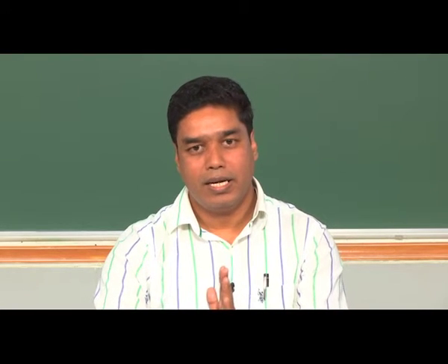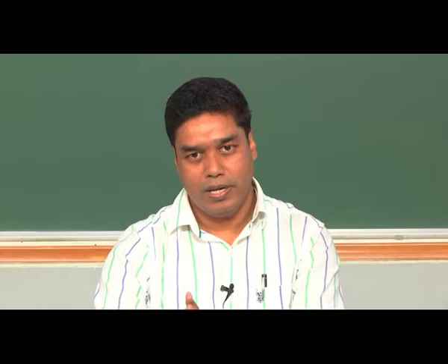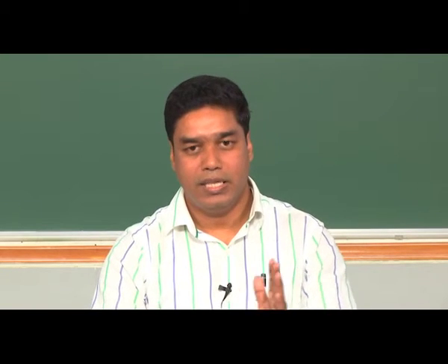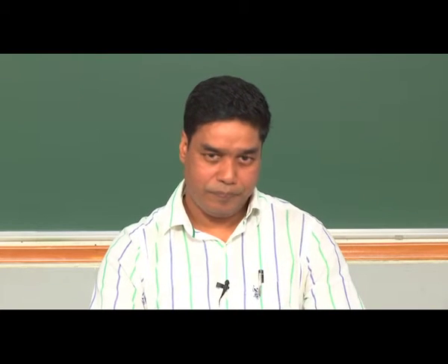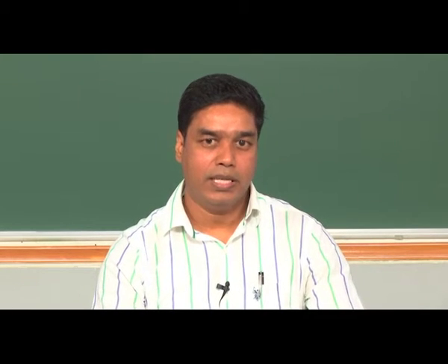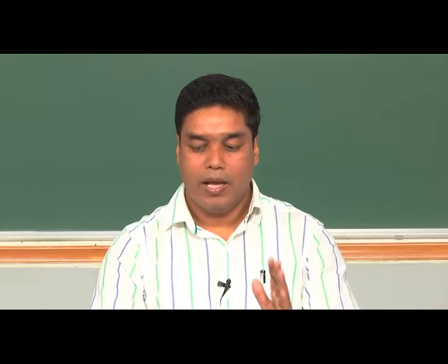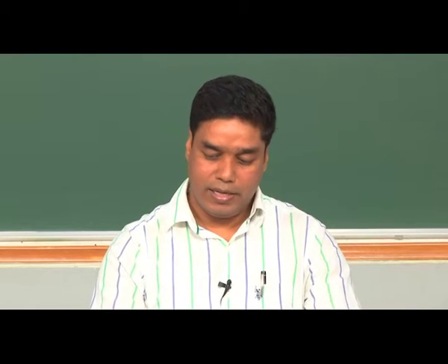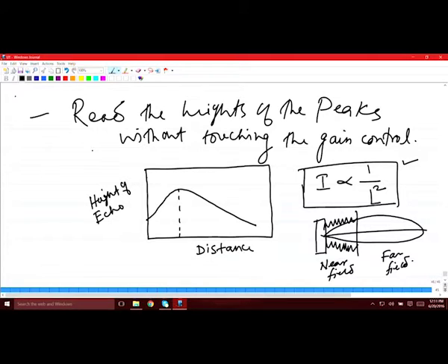Okay. On the other hand, if the echo is coming from a larger distance within the near field, then the receiving will be better and the signal intensity will be higher. Okay. Signal intensity which is being received by the probe within the near field will then increase as the distance is increased within the near field. Okay. So, that means in this case this region that you have where you see that the intensity is increasing